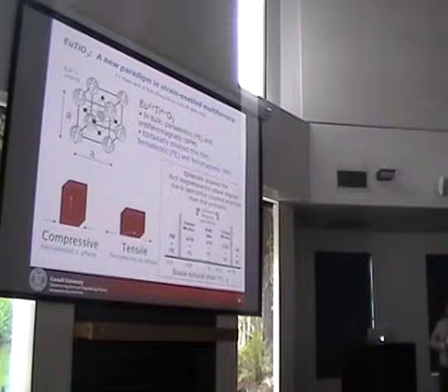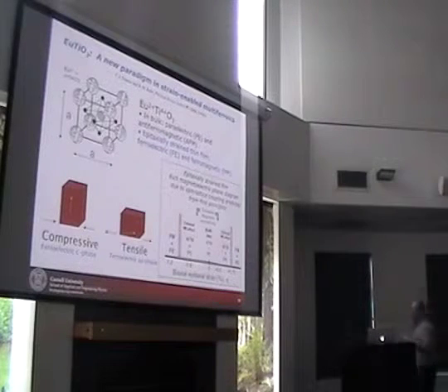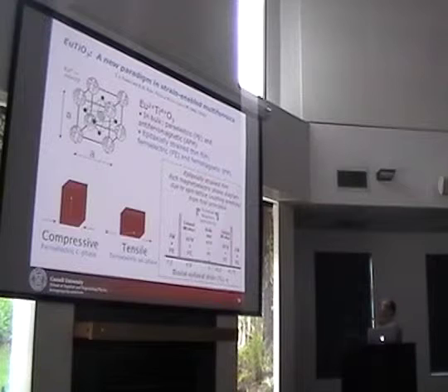Not really too important. We found a material realization, europium titanate. This is europium 2+, titanium 4+. Titanium 4+ is d0. Europium 2+ has a half-filled f shell. It has very large spins, J equals 7/2. We worked out this nice epitaxial phase diagram from first principles. Not really too important.